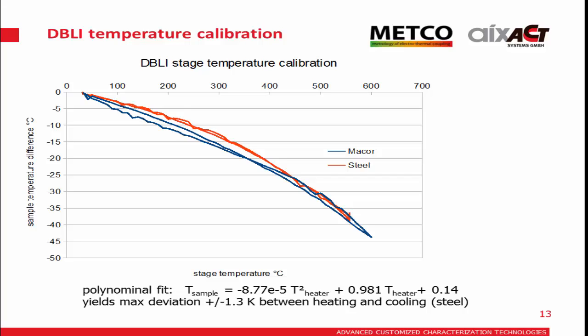So we took Macor and steel as two materials which have about a factor of 10 different thermal conductivity, but still they are within, let's say, 5 degrees.